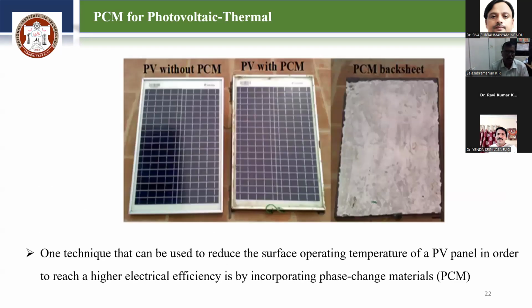So this is the experiment which we conducted in our laboratory. Here we can see the photovoltaic panel without PCM and the photovoltaic panel with PCM. Here we used the PCM as the back sheet to reduce the surface temperature of the PV cell, so the surface operating temperature can be reduced in order to improve the electrical efficiency.